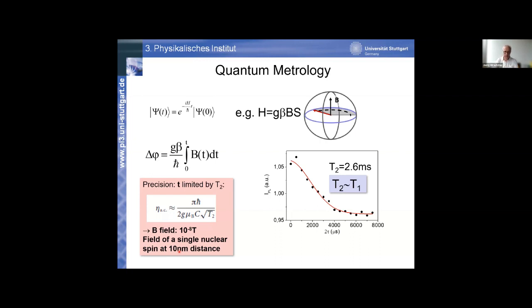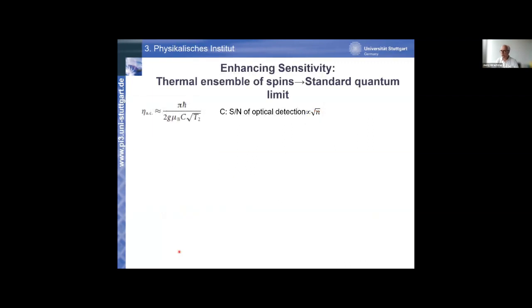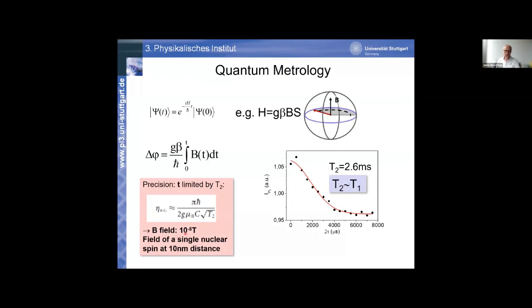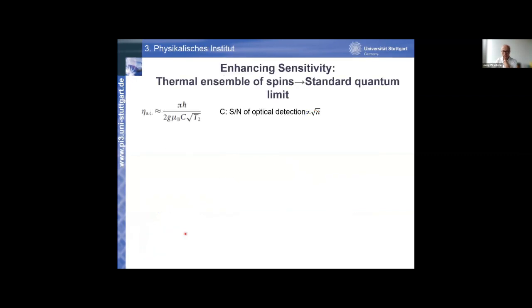All right. So if you want to gain sensitivity, if you want to go beyond this 10 to the minus 8, so roughly 10 nanotesla per single dopant atom, then what you can do is play with this C, in the sense that you increase the signal to noise ratio of your sensor. Once again, this is the diluted ensemble case, where we have no dipole interaction between the sensor atoms or sensor dopants, or any other means by which we achieve entanglement.